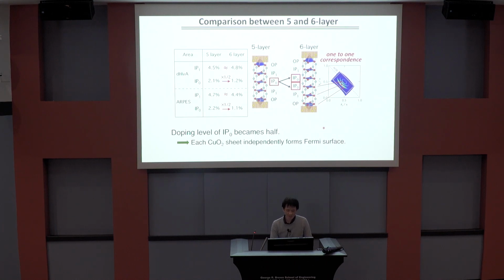Actually, this can be easily understood because in the 6-layer, the innermost layer becomes doubled, so the carrier concentration can also become half. This is also important because this clear division of carriers means the one-to-one correspondence between real space and momentum space is very good. That means this pocket comes from this layer and this arc comes from this layer—this kind of one-to-one correspondence really works.